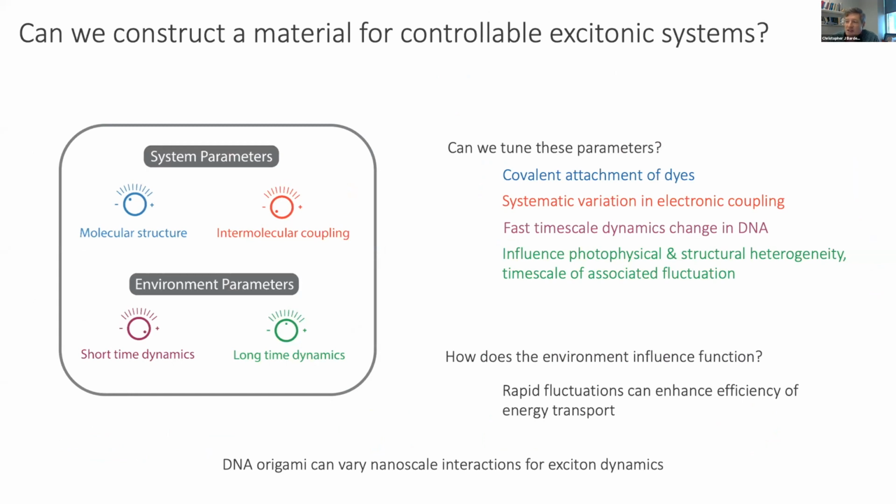So the first question is, the faster decay of the frequency correlation function in the DNA duplex seems to be faster than that in solution? Is that counterintuitive? No, because you're measuring really the influence of the local environment. So if you think about the local environment when you're in DNA, you're covalently attached to this charged system. Because you have all of the charges in the DNA and the local counter ions, those really nearby ions, any kind of motion or fluctuation in them is likely to have a dramatic influence. So you expect the collective action of them to lead to a faster decay. So in retrospect, it actually made a lot of sense, where it's the longer time scale behavior that may be hindered, or fluctuations that may be hindered by the environment, but the short time scale is actually going to be faster.